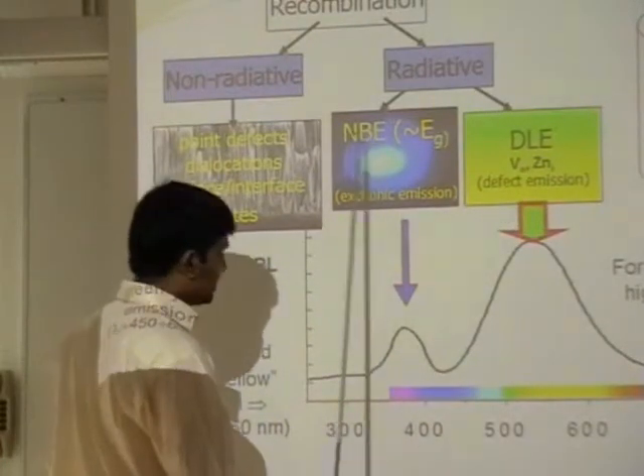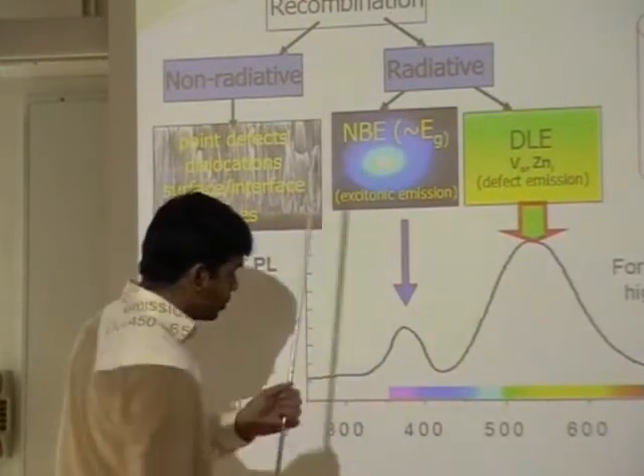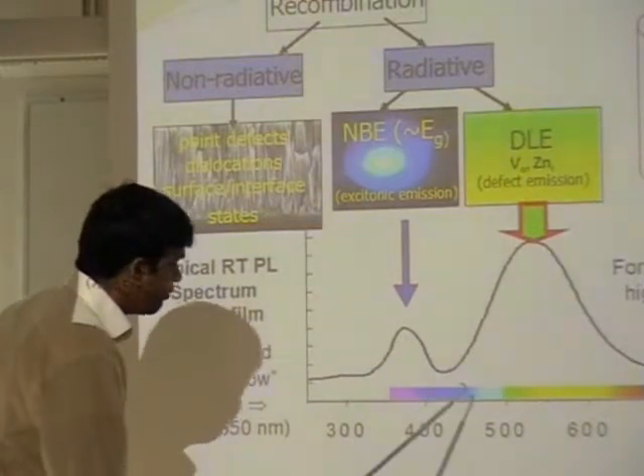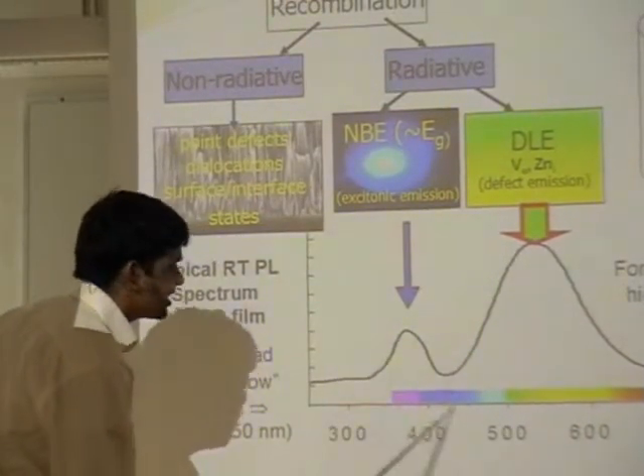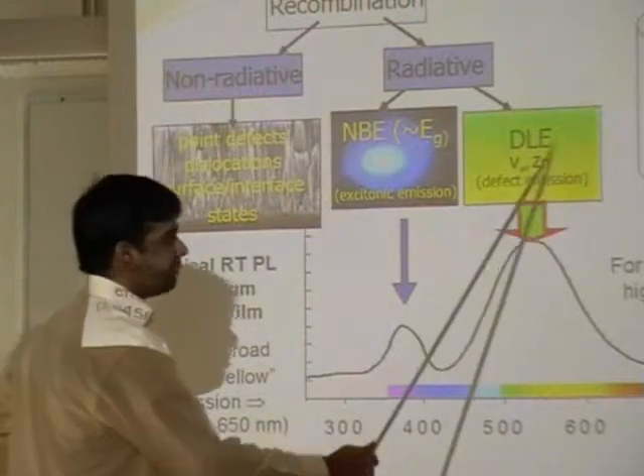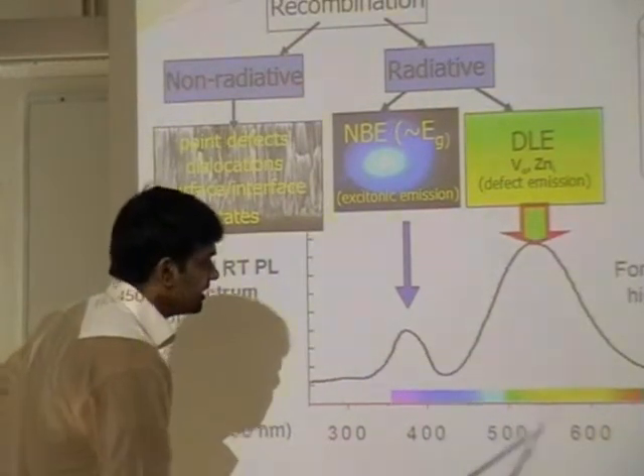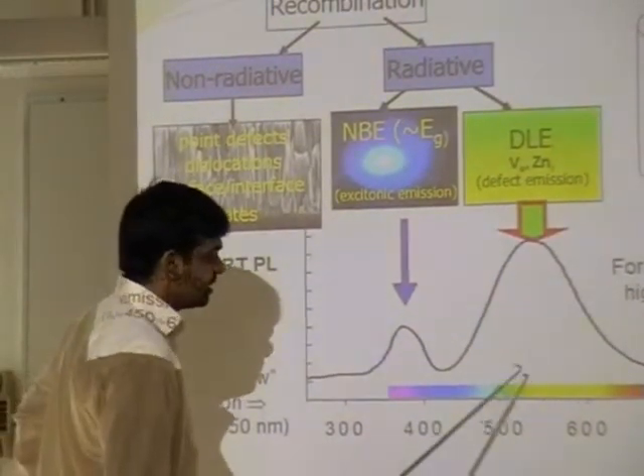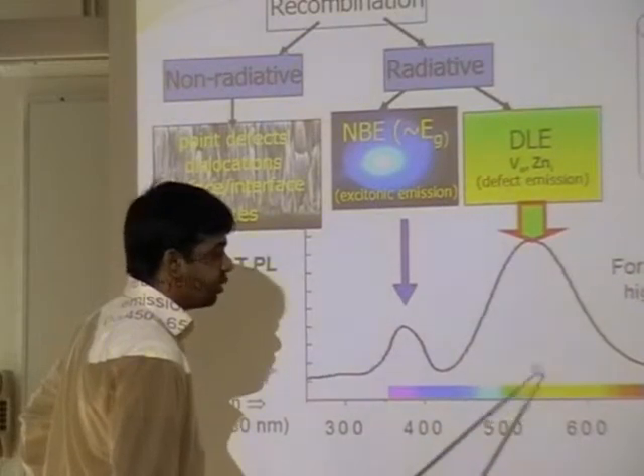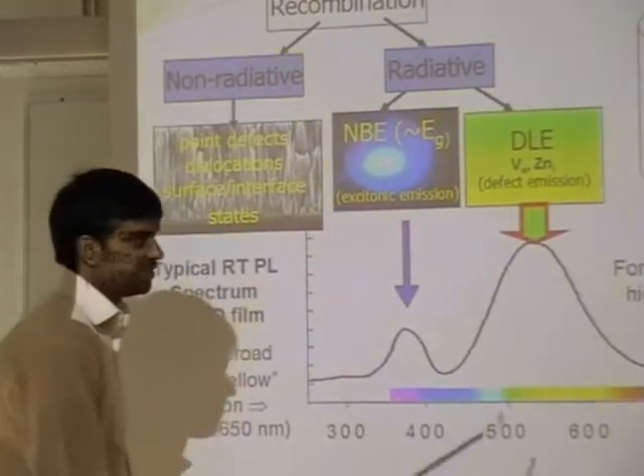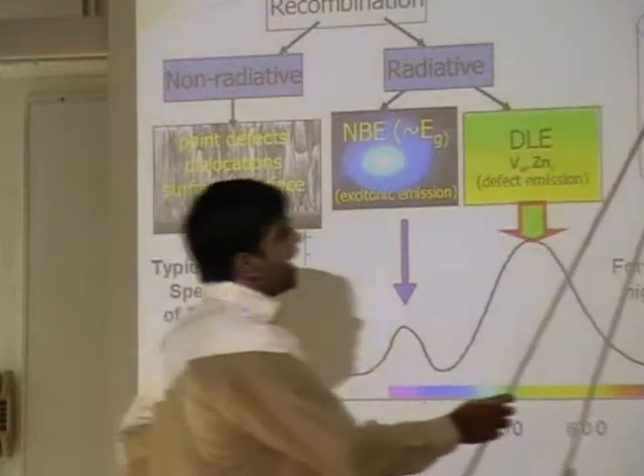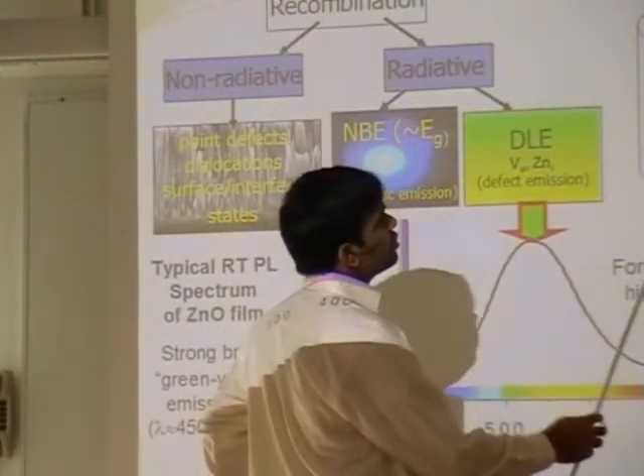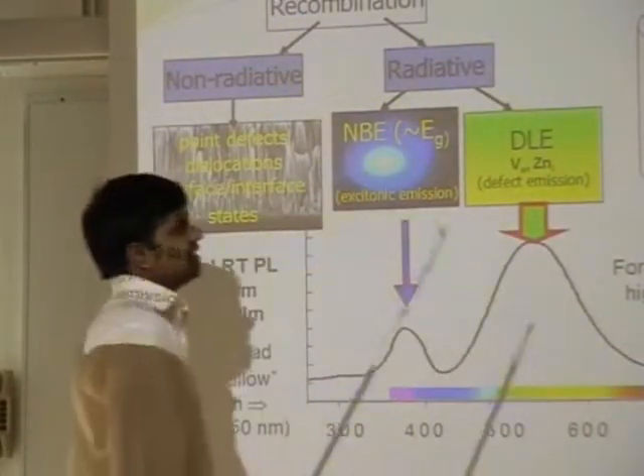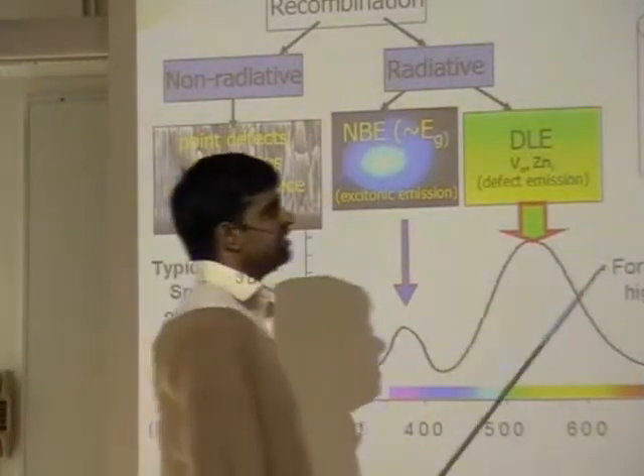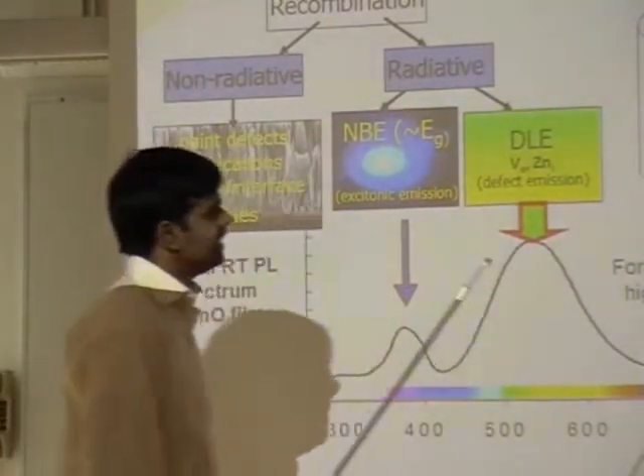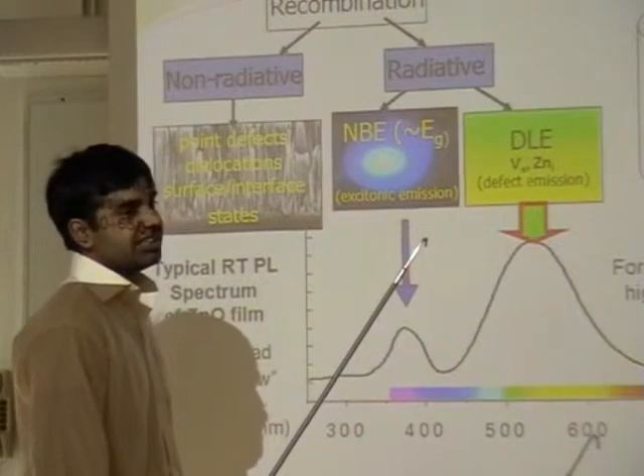The near band emission range is 375 to 400 nanometers. But the deep level emission is in this range. They emit green, yellow and orange emission. There is a high demand to obtain ultraviolet emission in zinc oxide, especially for light emitting diodes.